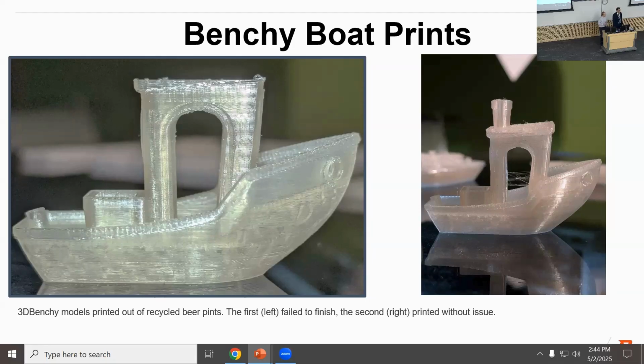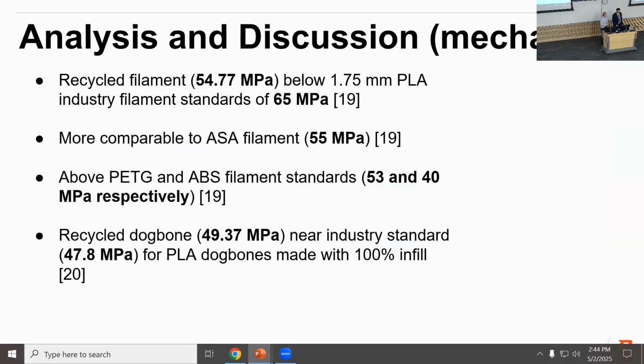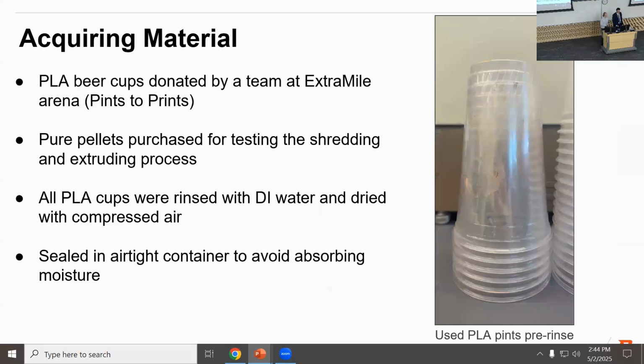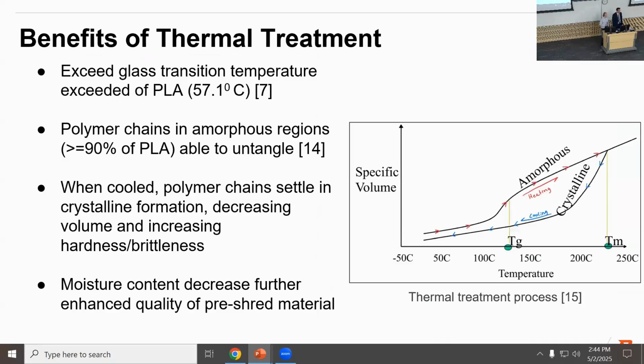So, before putting the shredded pieces into the extruder, you did the thermal processing, heating it up and then cooling it down. And the argument there is that by heating it up close to the melting temperature, after cooling down, we've got a crystalline polymer that's more brittle. Does it matter if you just cool it down enough? Can you process in a cold room, or how much did heating up and cooling down help with the processing?